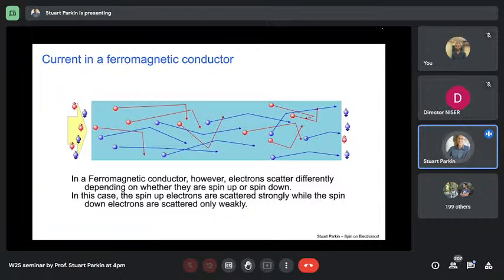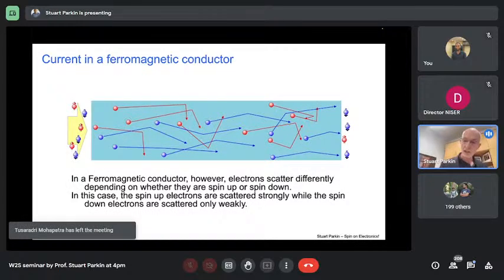And this was a concept that Neville Mott originally introduced. So the concept is that just by passing a current into a ferromagnetic metal, because of broken symmetry, because of the magnetization, the electrons are scattered at different rates. So the mean free path for spin up and spin down electrons is distinct, and the current is carried by electrons of one spin type.